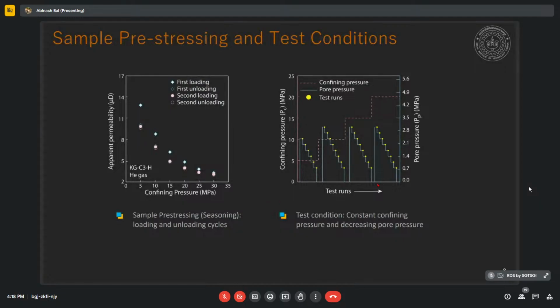But before measuring the apparent permeability, there are two very important things. One is pre-stressing, which we call seasoning of the sample. Why is it important? Because shale is a compressible matrix. Suppose when we start estimating the apparent permeability, we apply a loading cycle and unloading cycle. We found that at the same stress condition, loading and unloading form a hysteresis curve.